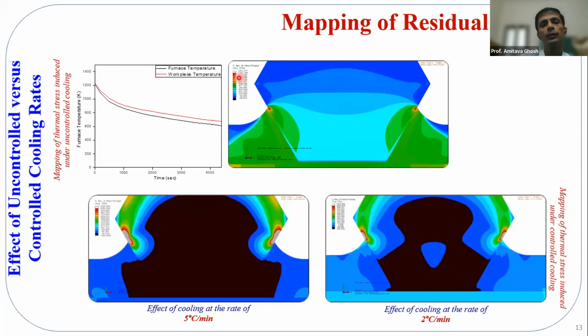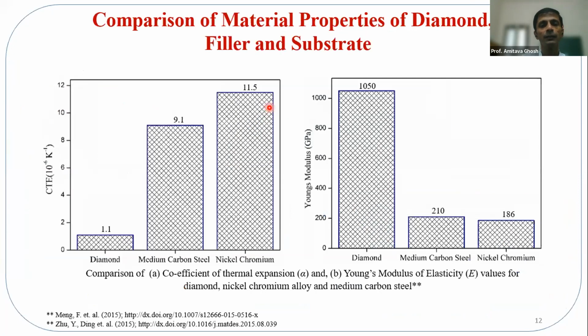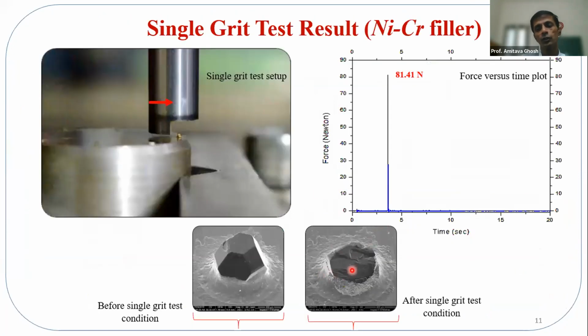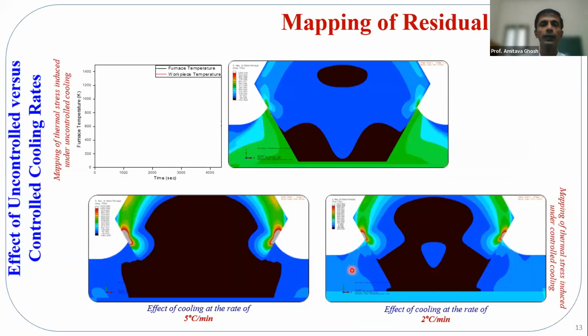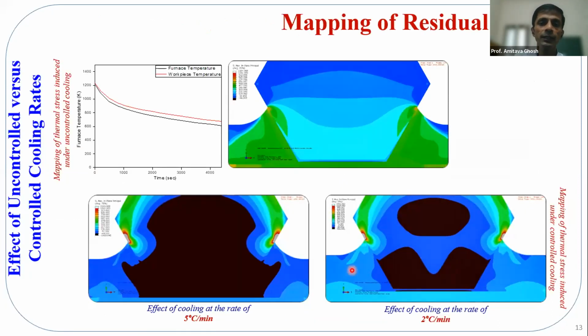Now, if we imagine that there is a load which is coming from left to this side and this way, what will happen? Because of the bending, this portion will be having additional tensile stress. So which will further go, and in particular, whatever energy spent here, it will simply cross the fracture toughness of the diamond, and finally the crack will be opened up here, and then simply it will propagate to the weakest directions, and finally we basically land up into the failure like bond level truncation. So this is exactly what is happening, and this is how the brazing metallurgy basically works.